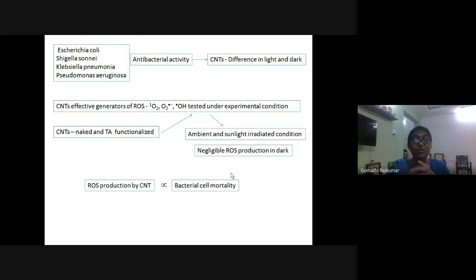So now the second part of our work: we tested if these nanoparticles could generate reactive oxygen species. However, we just took three radicals. One was singlet oxygen, the second one was superoxide, and the third one was the hydroxyl radical. I repeat, we tested only three oxy radical species. Using experimental conditions, we tested if the carbon nanotubes could generate these three oxy radicals.